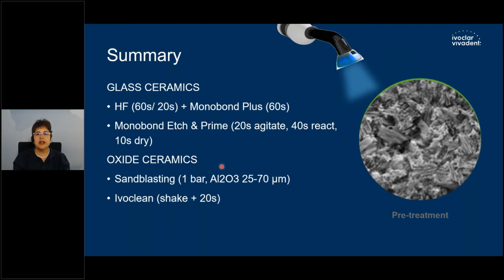On the other hand, we have our oxide ceramics. So you always need to sandblast to activate the surface with a minimum of 1 bar and with aluminium oxide particles between 25 and 70 microns. And if you make a try-in, we recommend to use Ivoclean. Important here is always to shake, and then you apply it for 20 seconds.